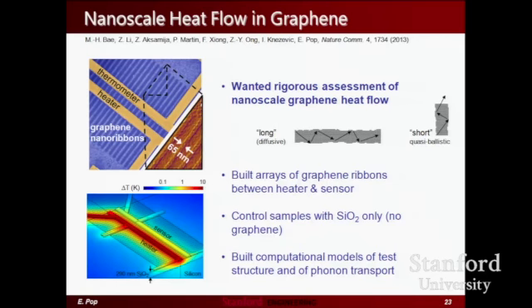But it's not happening near room temperature, so how does it affect me as an engineer who would like to have his electronics working at room temperature? So we had a hunch that graphene, one of the materials that we work with, which has extraordinarily high thermal conductivity, we had a hunch that these collision distances between phonons and electrons in graphene would actually be long enough to allow us to measure this effect at room temperature.